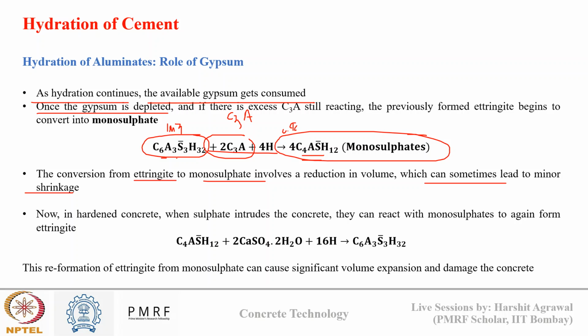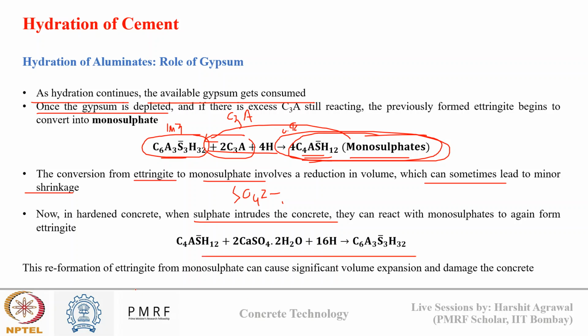Okay, and this reaction happens later on, not in the early stages. Now in hardened concrete, suppose I have monosulfates present. What happens if sulfate ions come from external sources, if sulfate ion comes inside concrete? This monosulfate can again convert back to ettringite, which will involve expansive reactions. Since ettringite to monosulfate conversion led to volume reduction, monosulfate to ettringite conversion will bring volume expansion.